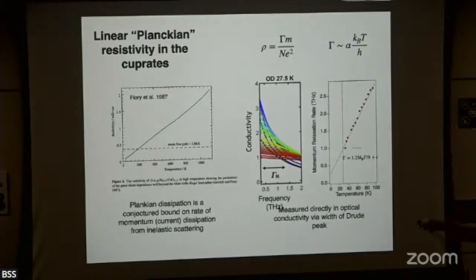Those are temperatures. Yeah. How do you extract the width? Yeah, so exactly, that's a good question. So this is a very flat curve here, so you can't get the width out very well, but we're measuring, I didn't show it, this is the real part, there's an imaginary part, and so that would be a slope here of finite width, a line that's going up like that. And the ratio of these, I mean, what we do is we fit it, but you can see it in the raw data. If I looked at the ratio of these quantities, that's omega times tau, right? So it just kind of comes right out at, again, a very, very simple level.